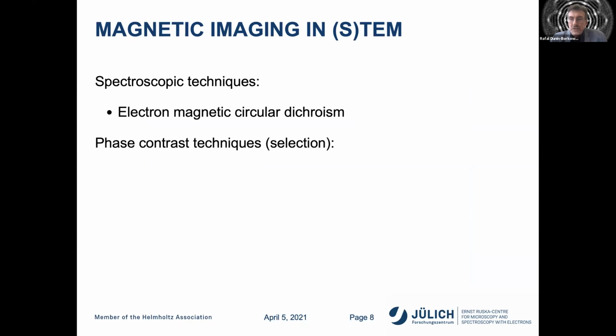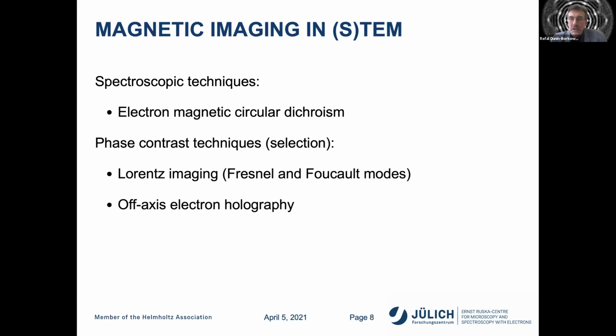And then there are phase contrast techniques. And these techniques are usually sensitive to the magnetic flux density B, and especially the magnetic flux density oriented in a direction perpendicular to the incident electron beam direction. And here we have some TEM techniques, for example, the Fresnel and the Foucault modes of Lorentz imaging. This is effectively defocused imaging and dark field imaging of magnetic microstructure. We have off-axis electron holography.